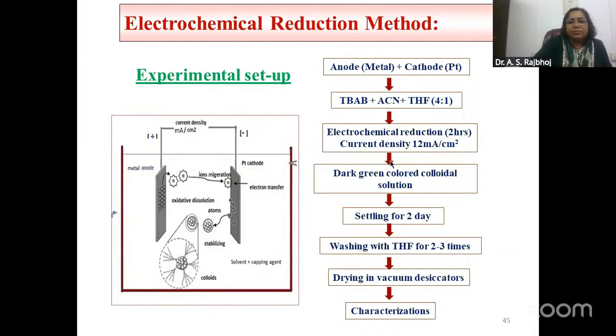Now an example given here is copper. You can see the dark green colored colloidal solution being formed here, and the settling of this colloidal solution requires at least 2 days. You can see in the figure, the positive one is the sacrificial anode and the platinum is negative. So what happens is that this metal anode releases its ions.